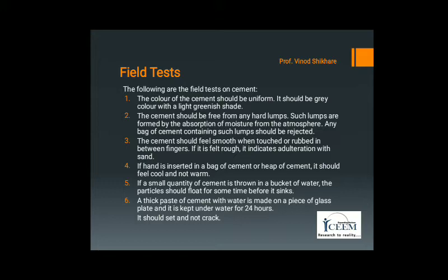Next test is to prepare a block of cement of dimension 25 mm by 25 mm by 200 mm. It is immersed in water for 7 days. It is then placed on supports 15 cm apart and loaded with a weight of about 34 kilograms. The block should not show any sign of failure.